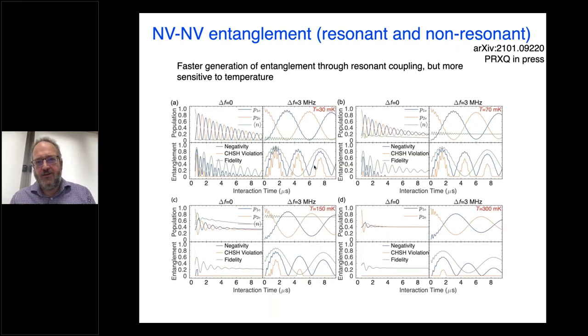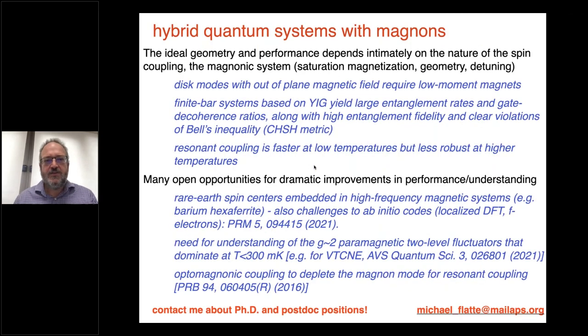Furthermore, we've compared the situation of resonant versus non-resonant as a function of temperature to find that if you're looking at the entanglement, you'll get faster generation of entanglement through resonant coupling, which makes sense, but it's going to be less robust. As you raise the temperature, you start to occupy the magnon modes, which gives you a variation in the coupling via the magnon modes, which shows up as noise. So at higher temperatures, meaning above 150 millikelvin, you're really going to want to do non-resonant coupling to get the NV-NV entanglement.